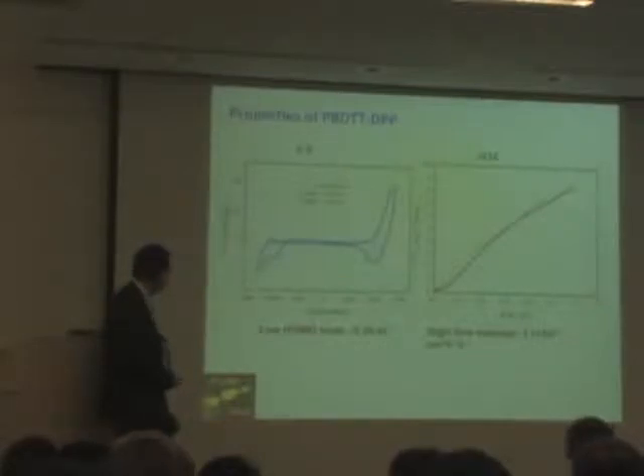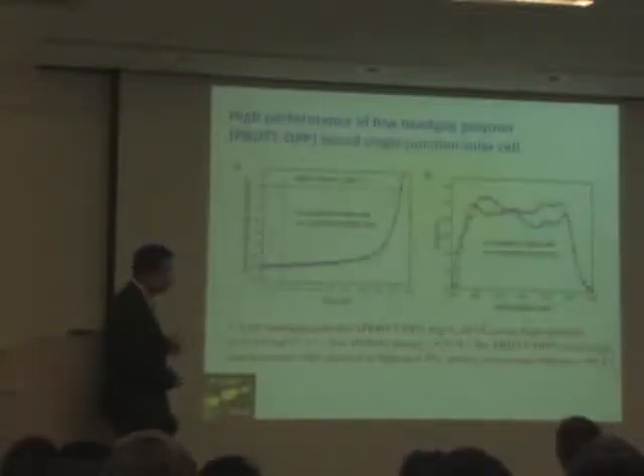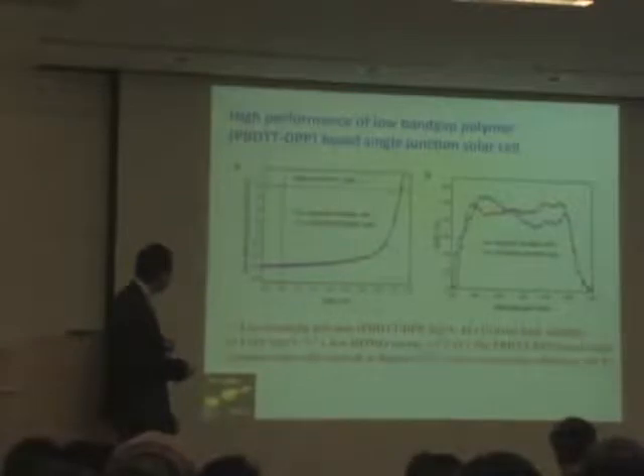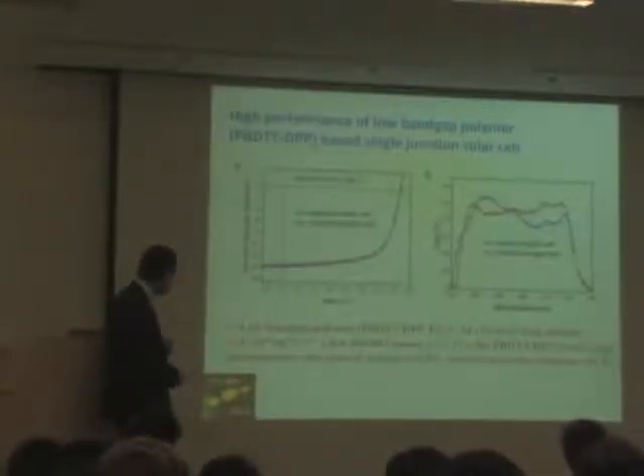So we have mixed it with the PC70BM, and this is the broad spectrum. Here are a regular single layer device and an inverted single layer device. These two devices come out almost identical. So the low bandgap polymer has a high mobility and a low HOMO level, and the base single junction device shows about 6.5% power conversion efficiency.